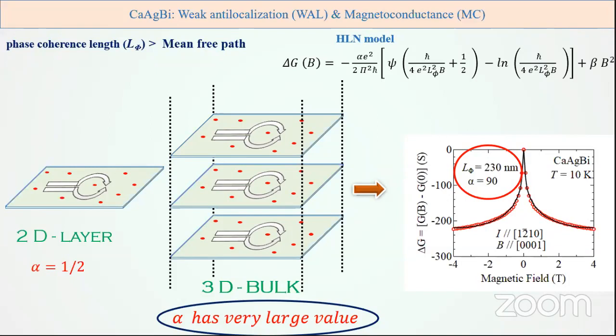In a standard topological insulator, once you break the time reversal symmetry by a large magnetic field, eventually the 2D surface states will go, and it will primarily be a 3-dimensional system rather than a 2-dimensional system. The question is whether the beta value is reasonable enough that you say it is only coming because of the classical component in the magnetic field, and not because there is somehow a crossover from 2D physics to 3D physics.